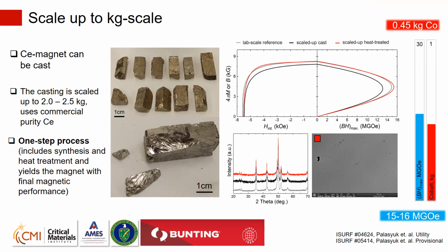How do you control anisotropic direction, assuming it isn't isotropic? It's not anisotropic yet. Casting is not anisotropic. And how do I control? I want to develop directional casting, because the casting that we have right now is not directional. And the demagnetization curves that you see are from the wax aligned material.